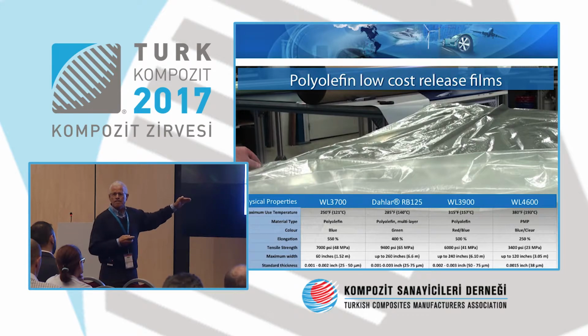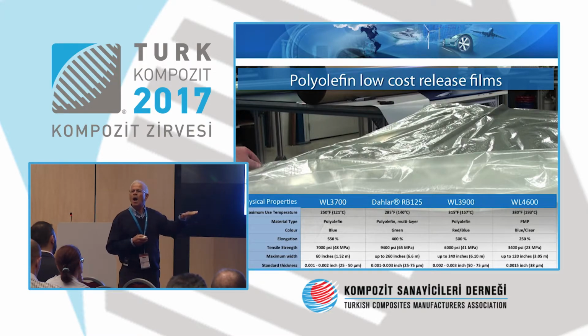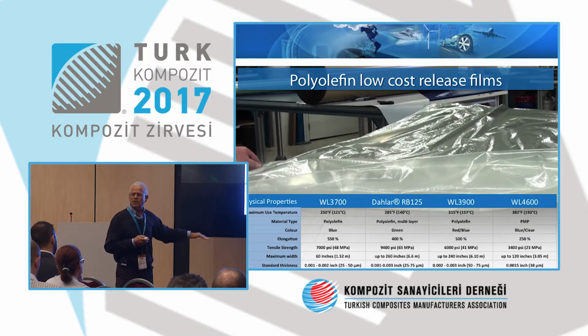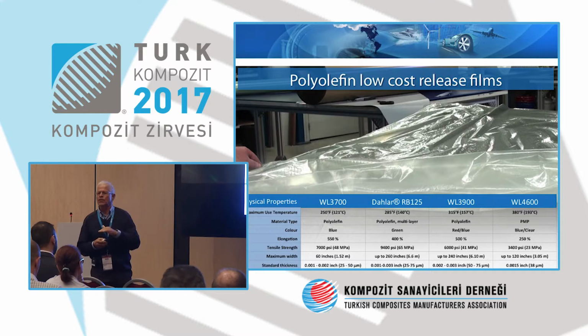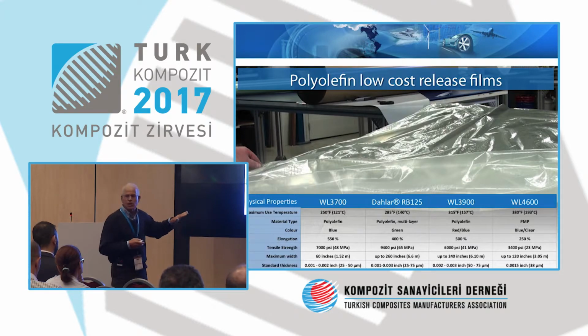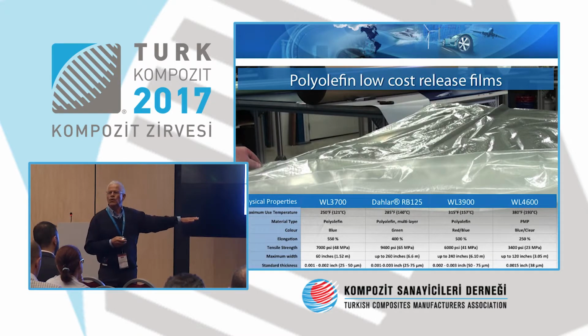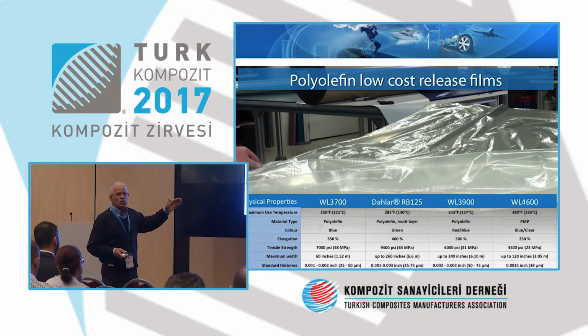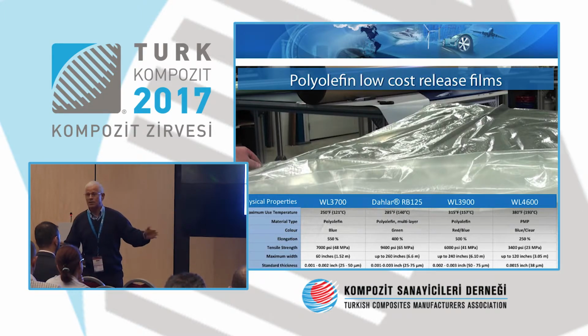This is the same family of films, only lower price and lower temperature. The previous sheet, you can use those films up to 260 degrees C. This one, you can only go to 120, 130 cures. It's good for infusing a big boat, or for a windmill blade, or wind energy blade, okay? You would not use this film to make an aeronautic part, because you lose your part.